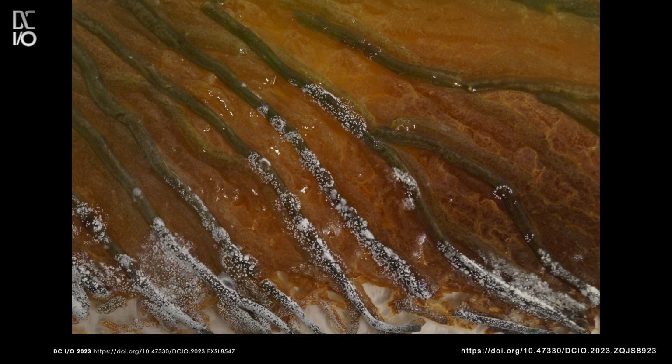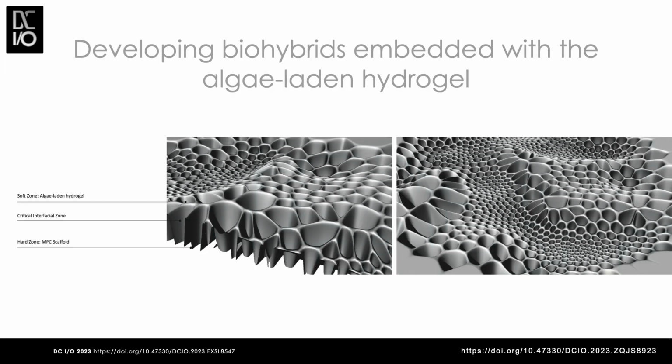We also wanted to do this very fun experiment in order to understand how the 3D printed panels actually behave once you stop maintaining them. And here you're seeing that the viscous materials are actually beginning to either dissolve and be colonized by bacteria that might be present within its environment. And over another 1 month's period, it really started to decay, dry. So because the material is about 85 to 90% water, the rate of evaporation actually leaves behind a very small amount of the material, which is very easily decayed and dissolved under natural conditions.